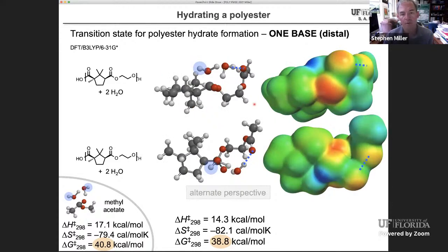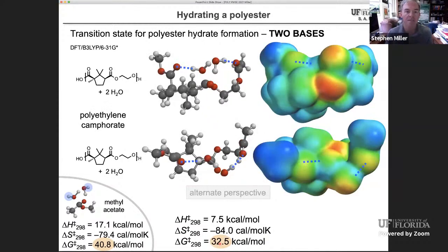What if we approach our transition state with a basic ester from the other side of our polymer chain? Well, that will dissipate charge buildup at this hydrogen atom, but of course not the other one. Got the same answer here. It's a little bit more enthalpically favorable, a little less entropically favorable, and you get almost the same overall barrier. But what if you bring both flanking ester groups near that 6-member transition state? You get to attenuate the charge buildup on both of these hydrogen atoms that are exocyclic to this 6-member transition state. And when you do that, you vastly lower the enthalpy barrier.